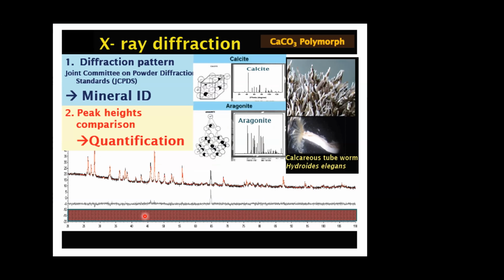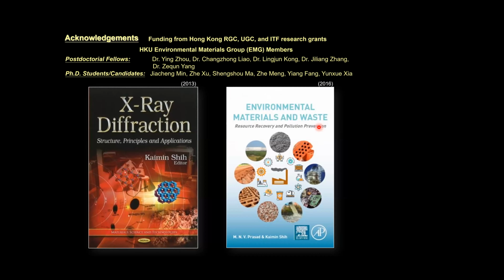Lastly, we also can work with biologists. For example, calcium carbonate is usually in the natural form of calcite or aragonite, and a lot of them are the so-called bones of the biomineralization process. In different biological processes, starting from calcium carbonate, it might be aragonite in a certain environment and at a certain age change to calcite. They're all calcium carbonate, so you cannot actually use chemical composition to identify them. You have to look at the mineral phase, which is X-ray diffraction. And in order to quantify their different reaction stages, the quantitative way is the way that you are going to use.